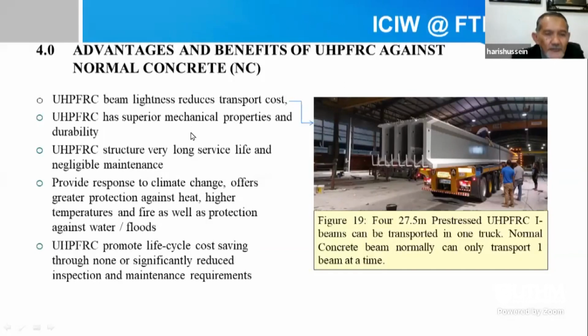Two, ultra-high performance fiber reinforced concrete has superior mechanical properties and durability. As shown earlier, the compressive strength is more than 150 MPa, and the tensile strength is more than or equal to 8 MPa, compared to normal concrete of 50 MPa, which is 2-3 times higher. And then ultra-high performance fiber reinforced concrete structure have very long service life and negligible maintenance. By looking at the surface of the beam, it can be seen that it's more aesthetic compared to normal concrete.